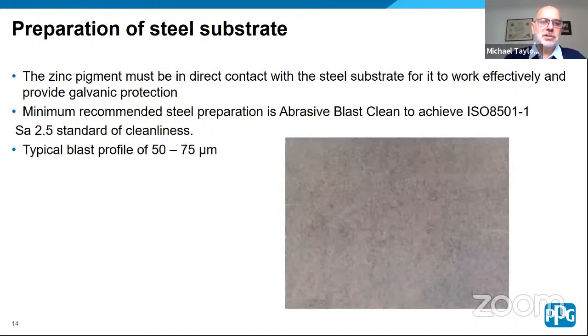In terms of preparation of the steel substrate for applying zinc coatings, it's very important that the zinc pigments have direct contact with the steel substrate. You have to have that electrical contact between the two metals. The minimum recommended steel preparation is to abrasive blast clean to achieve SA 2.5 standard of cleanliness, and typically the profile would be 50 to 75 microns. It's because of the way that you want the zinc to work in terms of electrical contact between that and the steel. There's no point in putting a zinc-rich coating over the top of another non-zinc coating, because obviously you're breaking the contact.